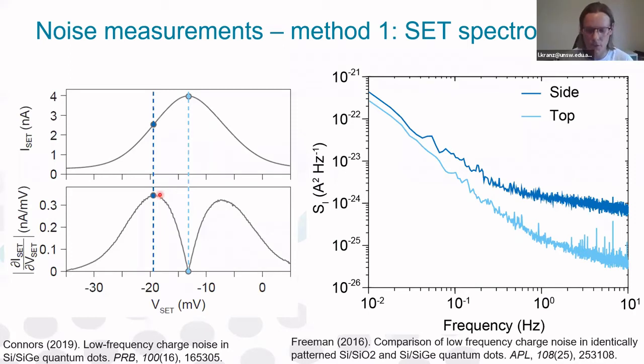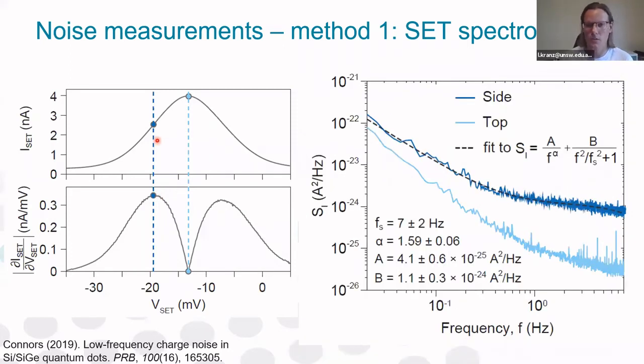And so first we want to figure out what kind of function would describe the spectrum that we measure. So we find a good fit with this equation shown here, and the fit is shown with this dashed line. And this equation basically has two contributions, the power law contribution and the Lorentzian contribution. As I mentioned before, the power law function would correspond to an ensemble of two-level fluctuators, while a Lorentzian function would correspond to a single two-level fluctuator. So we think we have a combination of both in this device, and this has been observed in other systems as well.